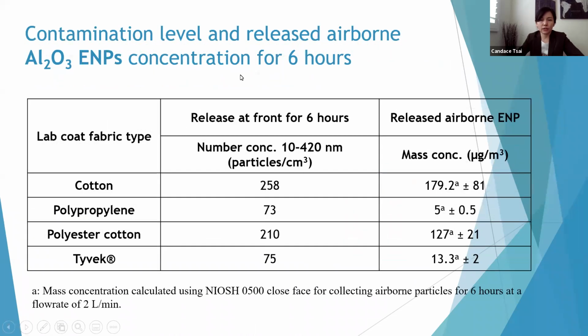This is the 6-hour data. Remember the second set of experiments, we ran this for 6 hours, and we found the result is consistent with the 30-minute experiment. We still see much higher concentration of release from cotton and polyester cotton, and it's pretty low on Tyvek and polypropylene - you can see the mass concentrations are very different.